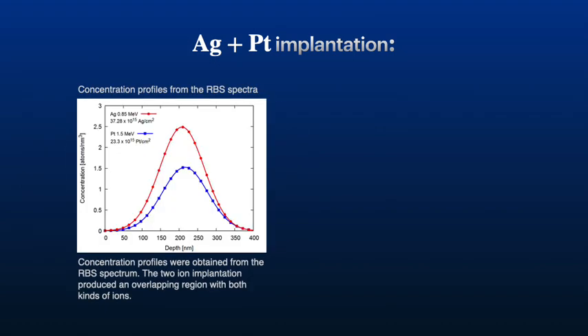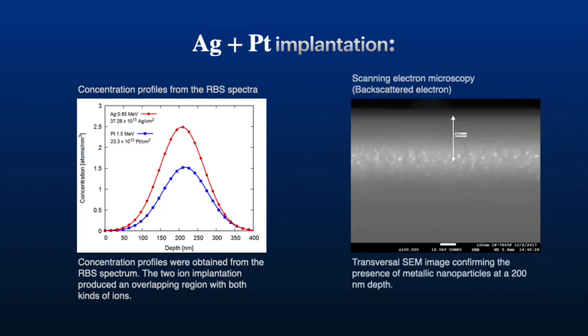Silver ions were initially implanted into a second set of pristine samples, and without any annealing, platinum ions were then implanted. Final annealing promoted the silver-platinum nanoparticles. Rutherford backscattering again confirmed that the two ion distributions overlap without long-range diffusion. Scanning electron microscopy confirmed the existence of nanospheres, as in the previous case.